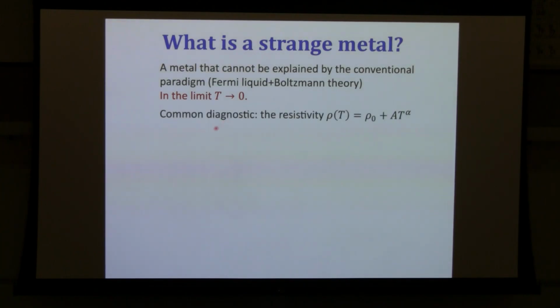Now a common diagnostic of such a behavior would be the electrical resistivity, which is the easiest thing to measure, and that would typically go like some constant at low temperature plus some power in temperature. Okay, and Fermi liquid theory for a metal would predict that this power should be 2. So what people find in certain systems is power law behavior with a power which is less than 2. Okay, eerily often this power is 1.